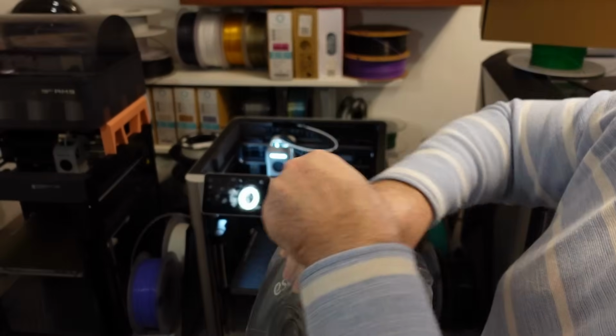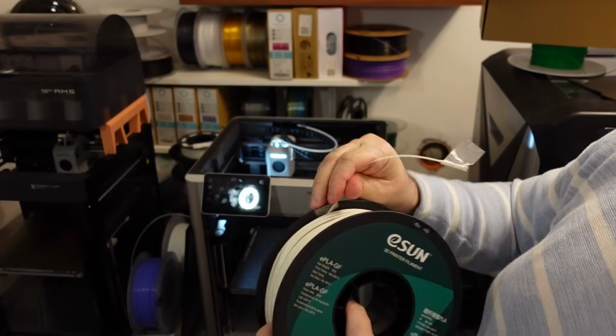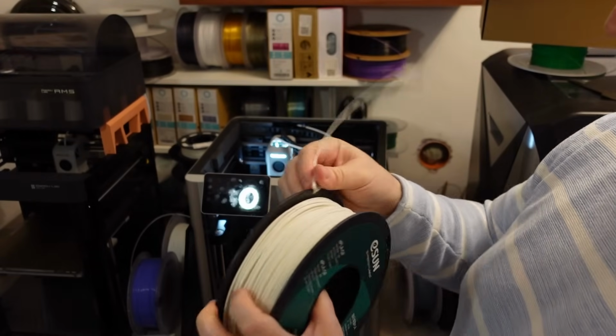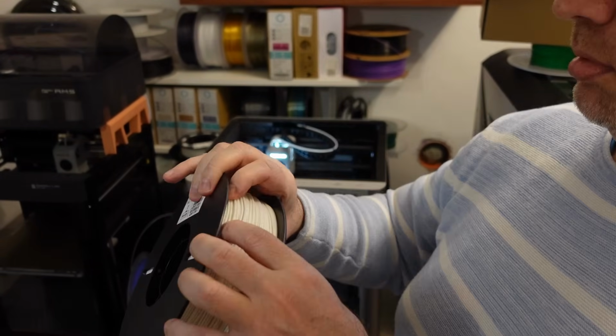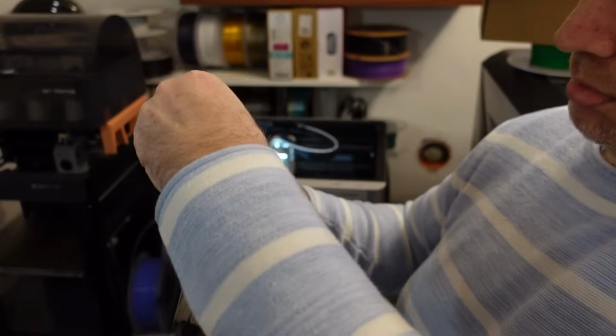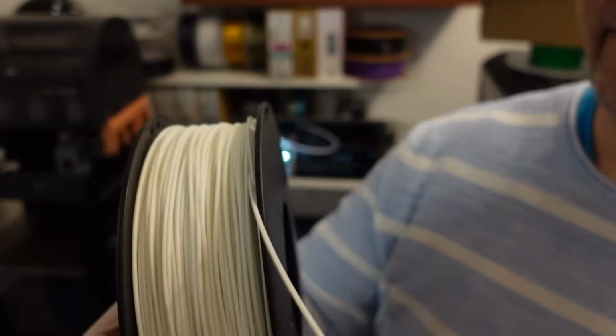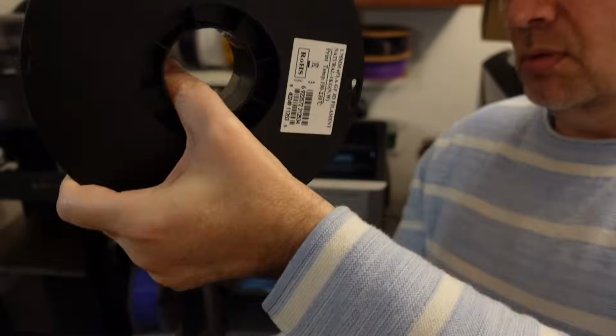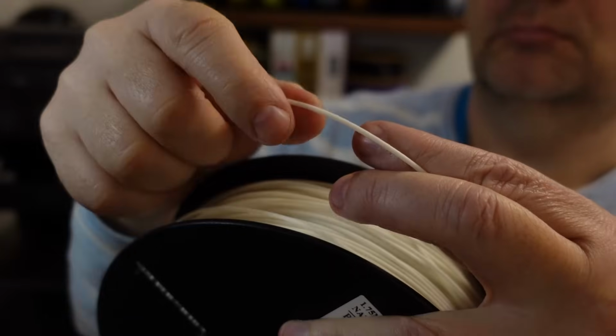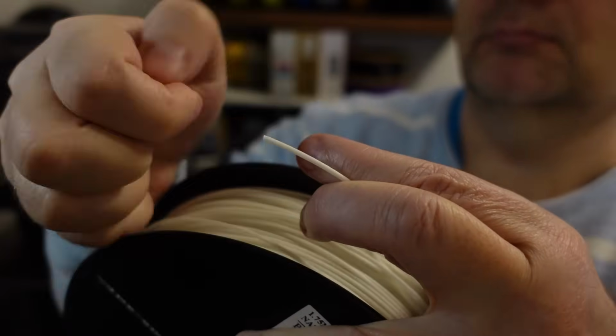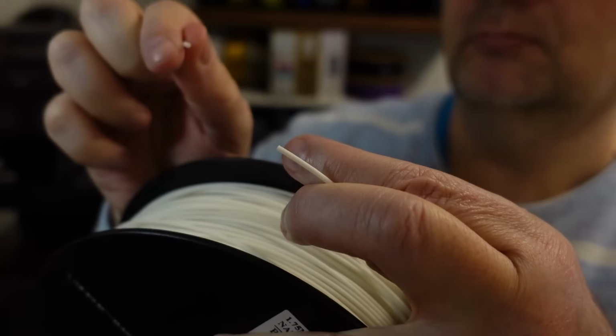I'm starting the printing with the glass fiber filament. I noticed the end of the filament is locked with sticky tape, and when I tried to remove it, it actually broke off. From now on this is a very risky material because there is a danger that it will tangle or jam. So I unrolled 10 meters of the filament. Look how brittle this material is. I hope everything will be okay.